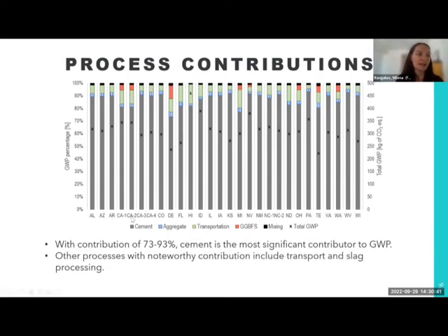Here, these names of the mixes are tied to the state. It's just one mix per state. It doesn't mean the state is doing good or bad. It's only used here as a data designation. However, one big takeaway from this graph is that you can see how big a portion of these bars is the gray color. So that's cement. Cement, based on this research, has a contribution between 73 and 93%. And as such, cement is the highest contributor to GWP of concrete.